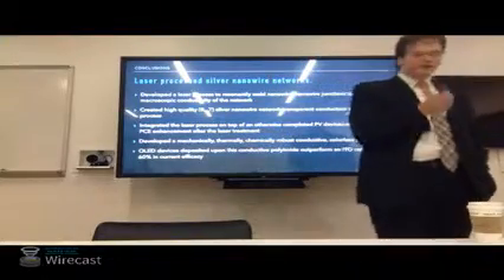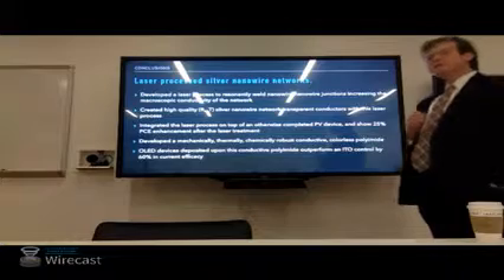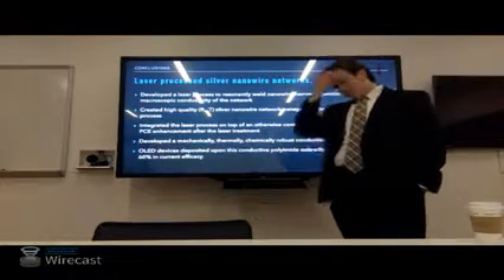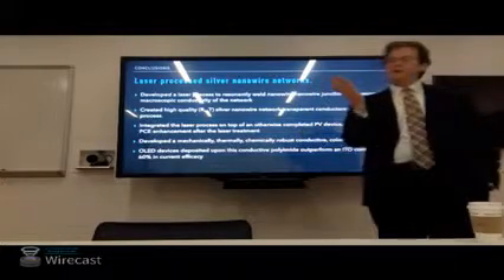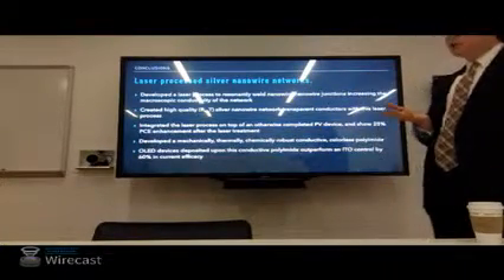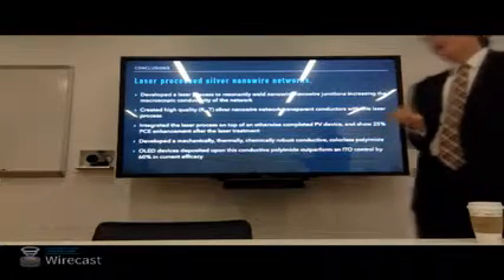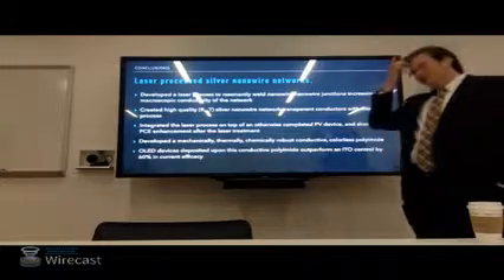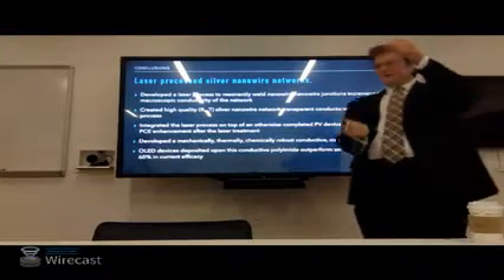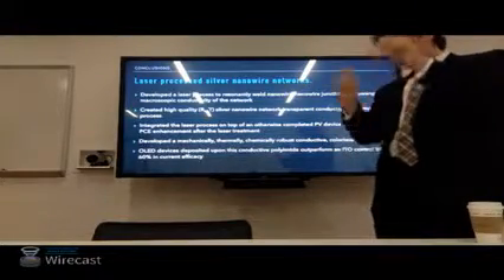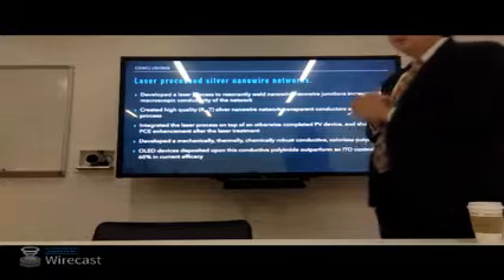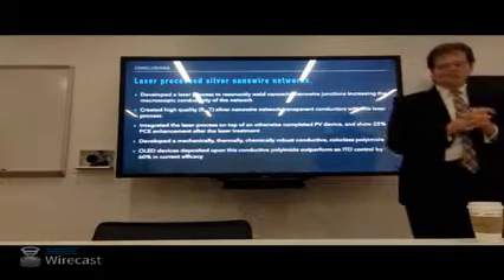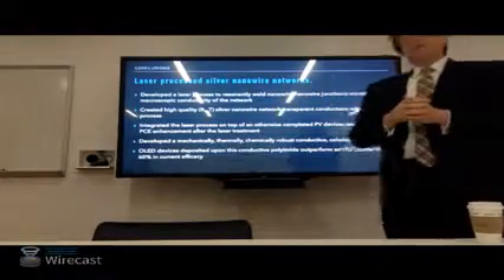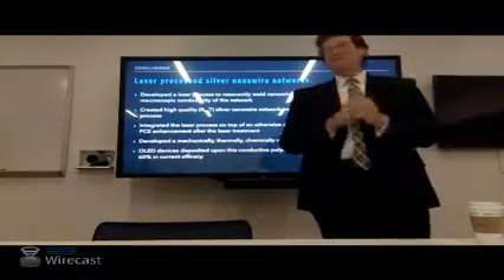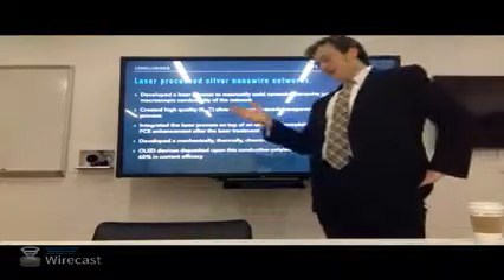The experiment you're referring to is where I made a piece of conductive polyimide, about 50 microns thick, maybe a little thicker than we'd use for a device. So it has nanowires at one surface. I used a laser to cut it into a dog bone shape just to try to ensure that the failure happened somewhere away from our contacts to our Instron. So you were grabbing it in. I was grabbing it with the tension, and then we used constant strain rate, something like 0.33% per second. Not too fast, not too slow. Room temperature, out in the uncontrolled atmosphere. And to be perfectly honest, probably our alignment wasn't great either. It's not impossible that we weren't pulling it straight up and down.